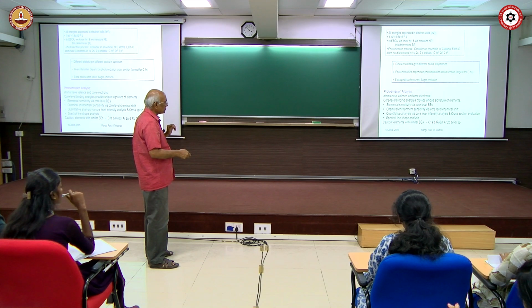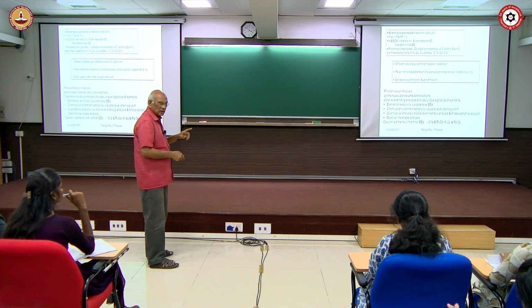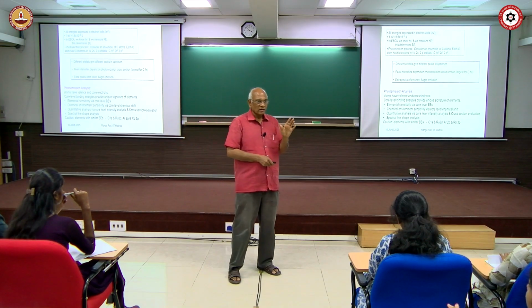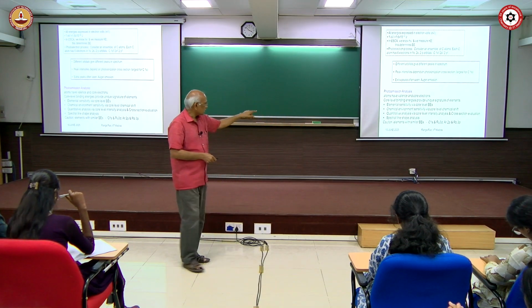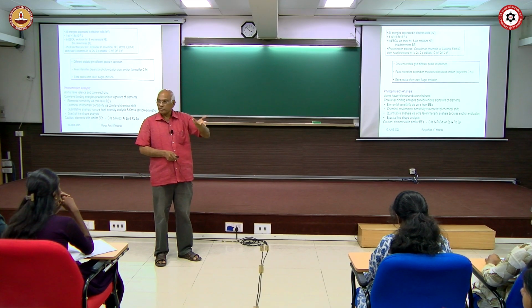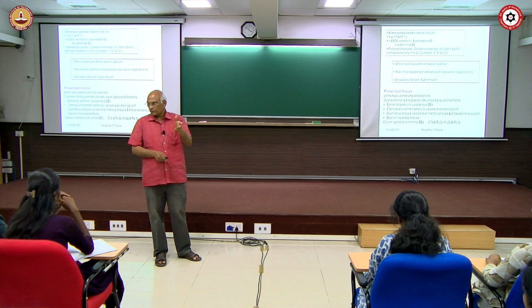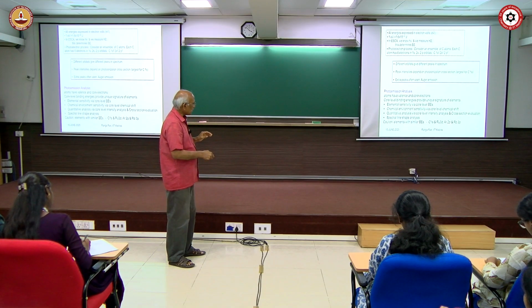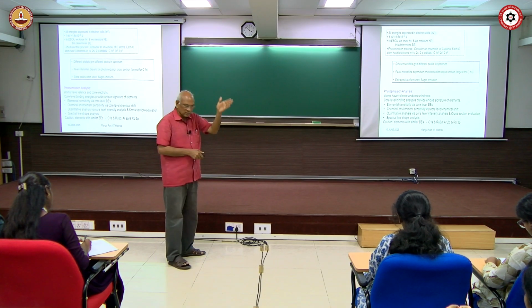Remember carbon 1s and ruthenium 3d come at exactly the same binding energy value. So when you are recording ruthenium 3d, you say that it is ruthenium 3d, but it may not be ruthenium 3d, it may be carbon 1s. There are a few things which you need to keep in mind. Similarly, argon 2p and rubidium 3p will come more or less at the same value.